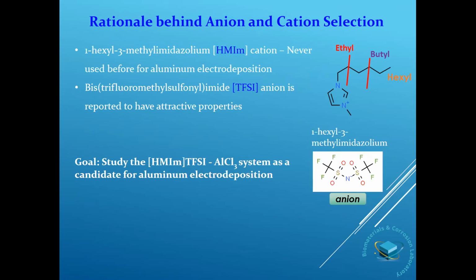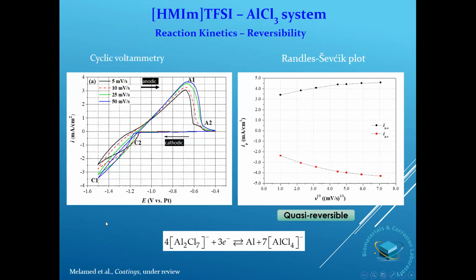What was our rationale, or why we hope that it will give good results, as I hope I will convince you. So on the left, you see this cyclic voltammetry at 4 different scan rates. Electrodeposition or reduction of aluminum starts at about minus 1.1 volts versus quasi-reference electrode, the platinum wire. The anodic peak A1 can be related to the oxidation potential of aluminum in the studied cell conditions. The broad window of anodic stripping may indicate that different aluminum complexes form, which is the A2 peak at slow scan rates, leading to a change in the ratio of the different aluminum species as the potential is scanned in the positive direction.